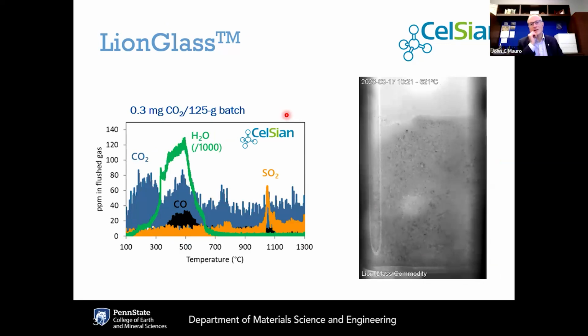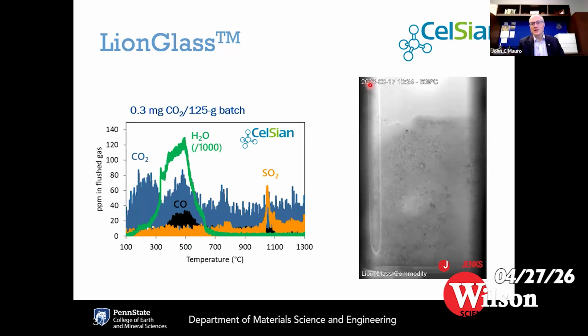Now let's compare this with LionGlass. This is the same experimental setup, now with LionGlass, and you can see we're starting at lower temperatures. This video is at 650 degrees C. You can already see some of the reaction kinetics happening at much lower temperatures. On the left, you can see the results from the gas chromatography, and the CO2 is now just in the noise. This is basically either trace impurities of carbonates or atmospheric CO2. If you integrate that, you get just 0.3 milligrams.